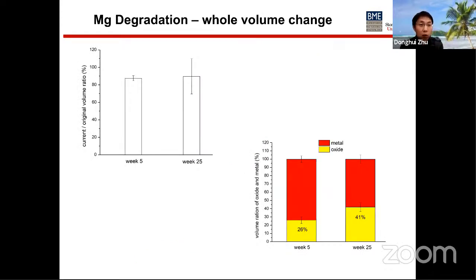So on the left is the whole volume of the implant, including both the metal and the degradation product, the metal oxide. About 90% of the original remains after 5 and 25 weeks. Although the whole volume shows no change, the ratio between the metal and the oxide switched. The percentage of oxide, magnesium oxide or other oxide, increased, indicating an ongoing biodegradation process of the implant.